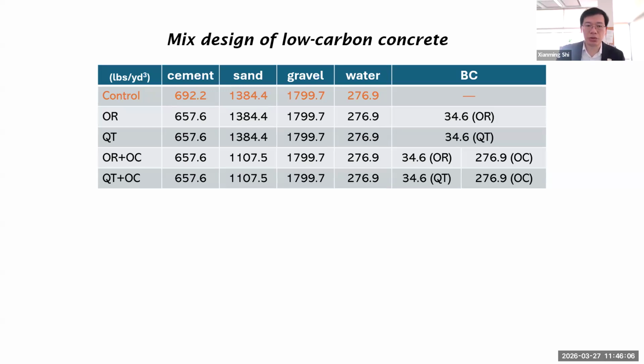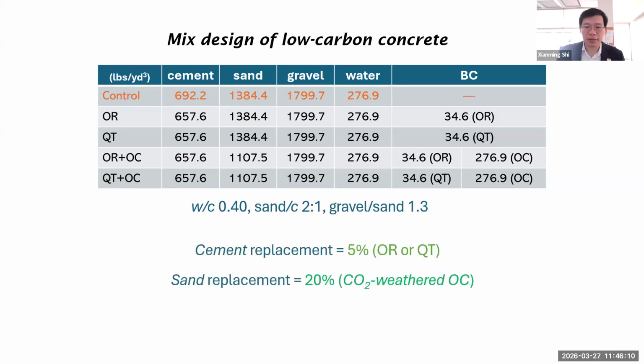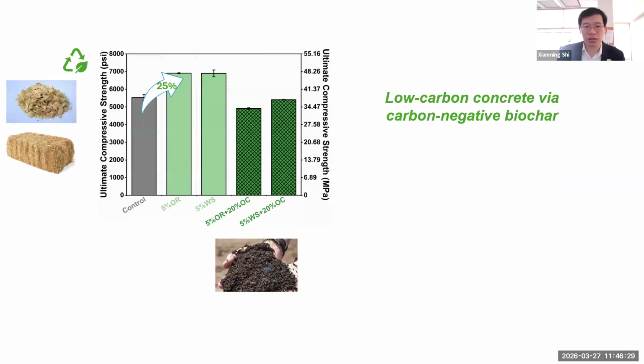So with that knowledge, now we move on to different mix designs. In this case, we started from paste and then mortar, and now we're into concrete. To accelerate the test, we cure them at 40 degrees Celsius, so sort of double the rate of hydration. And you can see the good news is that we're achieving about 25% better compressive strength at 28 days when we replace cement at 5%, either with the Oregon softwood chip derived biochar or the Washington State wheat straw derived biochar. Now, that strength is almost too high. We don't necessarily need that kind of strength at this moment.